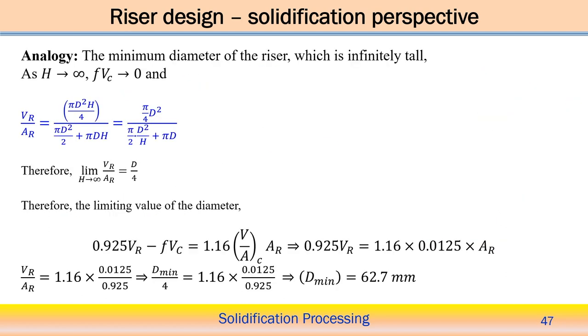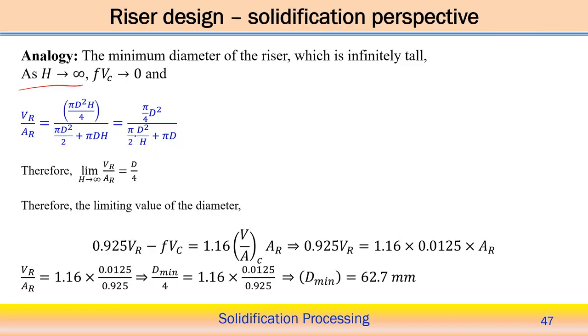And of course there is another point: what can be the minimum diameter of the riser, which in this case we are assuming infinitely tall. That can also be calculated using this particular expression. Now if we assume infinitely tall, if h tends to infinity, the fraction of the volume f, the feeding material from the casting, would also tend to 0 if h tends to infinity. That means it is an infinitely long cylinder.